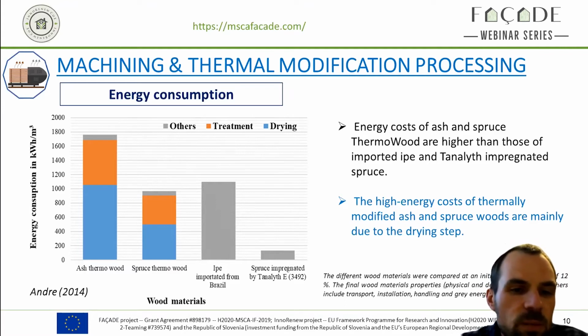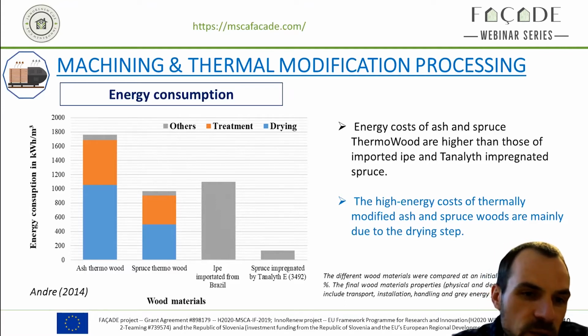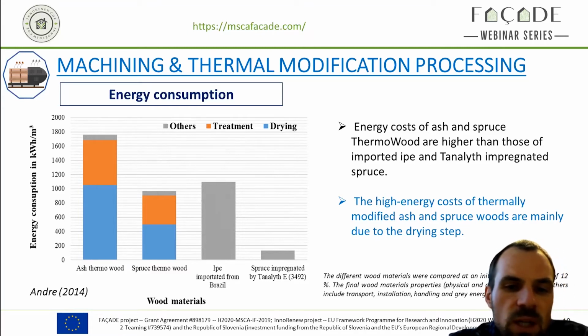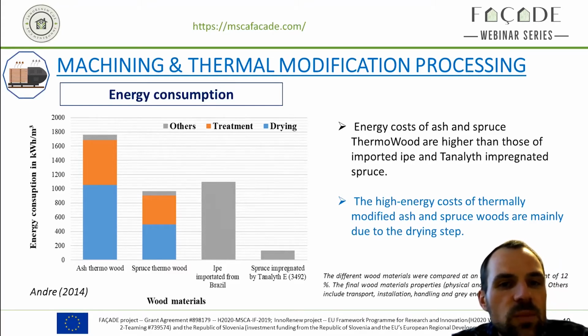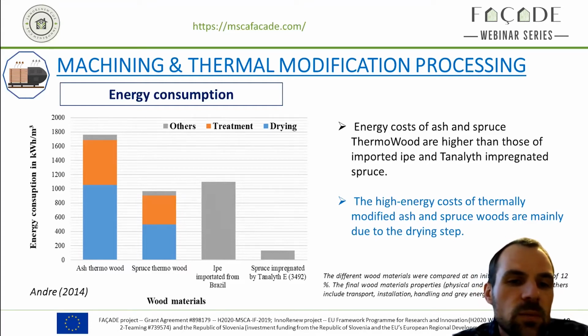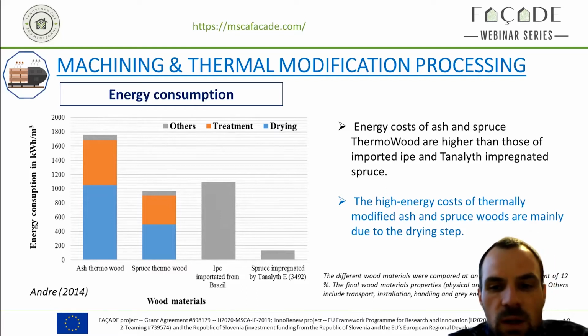But we can also observe, between the histograms in blue and orange, that the high energy cost of thermally modified woods is mainly due to the drying steps, whereas the energy cost of the thermal modification process itself is lower.